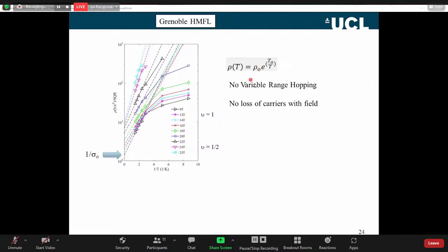Still don't see any variable range hopping. So the black triangle here is at 0 Tesla. There is absolutely no change when we're at filling factor 1. So filling factor 1 is a single spin polarized Landau level. We have the same behavior. There's no change to variable range hopping. In fact we can go up to half a Landau level, and we just get no variable range hopping.